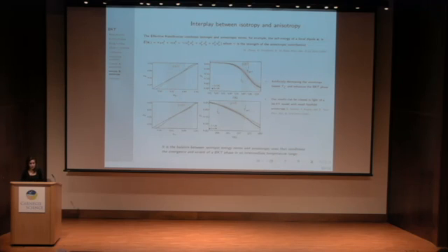So we set it to 0, we reiterated all the Binder analysis, and we did obtain an extended range with respect to the one mimicking the real system. Here it was about 5 Kelvin, and decreasing the anisotropy made it extend to about 13 Kelvin. So we think that these results should hold for any type of ferroelectric, provided that the balance is delicate enough between these two contributions.